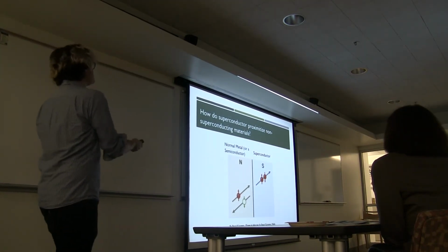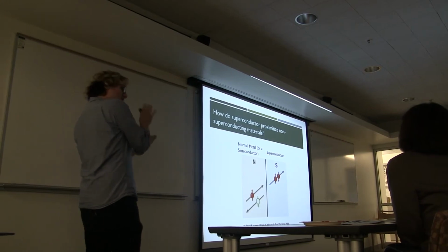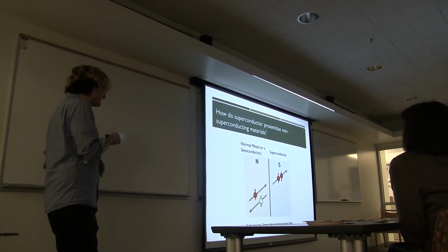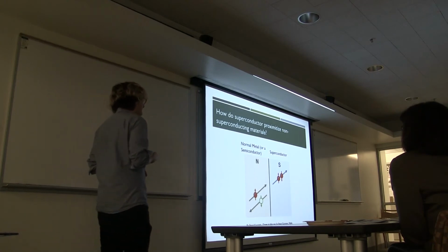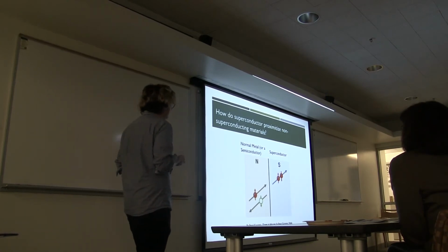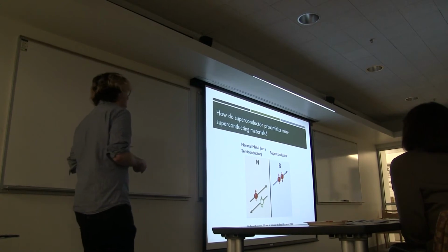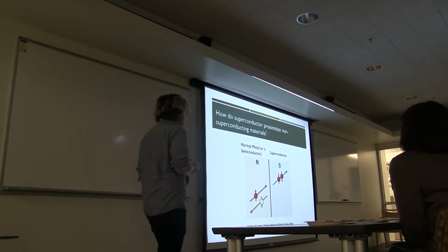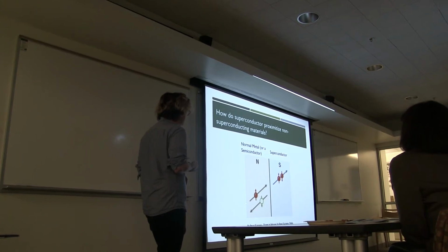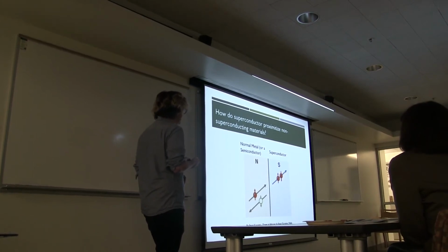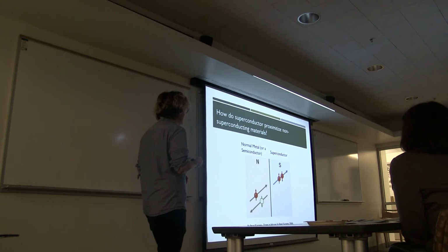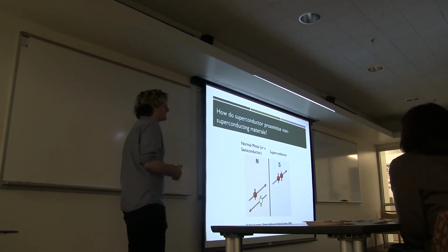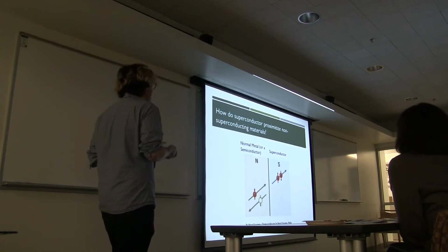So the question I'd like to pose is, what happens when you smush a superconductor and a not-a-superconductor together? Well, if the not-a-superconductor is a normal metal or a semiconductor, it's conducting. And it can communicate with the superconductor through a process called Andreev reflection. So if you imagine that there's a normal electron heading towards this interface, it can reflect as a hole, and then a Cooper pair, which are the fundamental charge carriers in a superconductor, can go in the other direction.